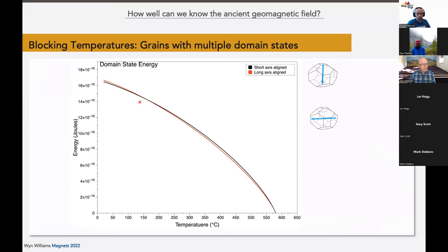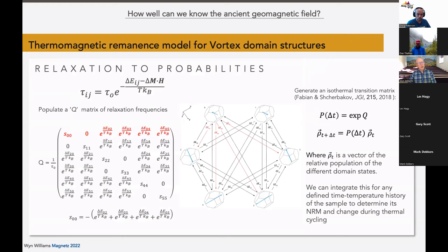And what they found was that between 50 and 90 percent of the remnants unblock either below or above that blocking temperature of the PTRM. None of the samples that they show here actually obey that reciprocity law. Even the smallest grains, the 600 nanometers or 1000 nanometer grains actually don't obey that reciprocity law. So in Thellier intensity experiments this effect would result in a curvature of the data in the Arai plots shown here on the right hand side with actually no indication of whether the average gradient gives an under or over estimate of the ancient field.